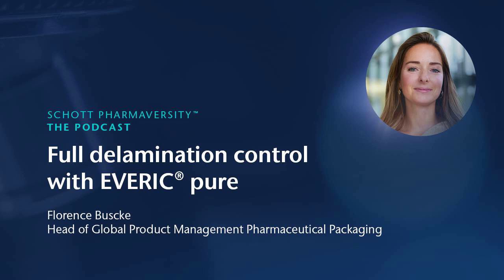So talking now more in the region of delamination, because you did also ask this, we can distinguish two things for leachables. One is a hydrogen attack. This is in the acid range below pH of 7. Here you have an ion exchange and a rise of pH. In the alkaline region with a pH higher than 7, we talk more about a hydroxide ion attack. And this attack releases network modifiers into the solution, and this attack is continuous.